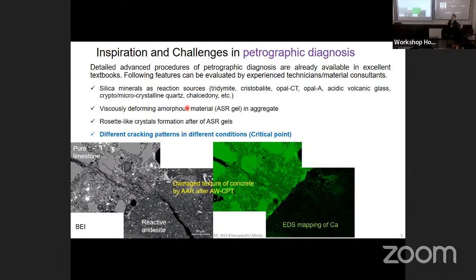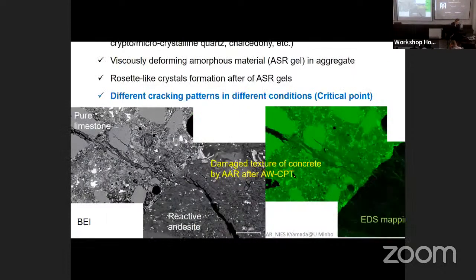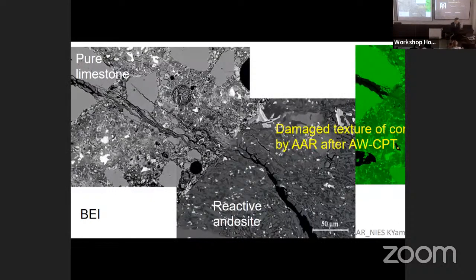generated. This is very viscous, generated inside the aggregate. And this gel is confined by the cement paste. Then expansive pressure accumulates inside the aggregate. Then beyond some critical value, cracks are generated from the aggregate. This is a reactive andesite. You can see a crack from here expanding into the cement paste.